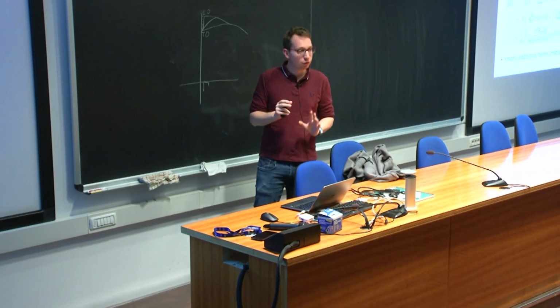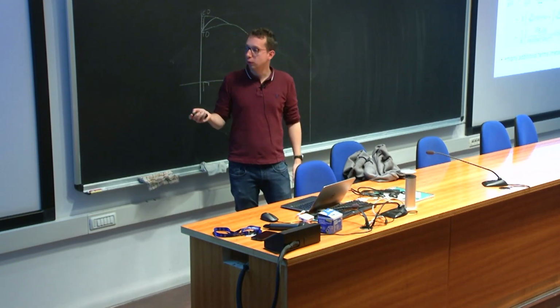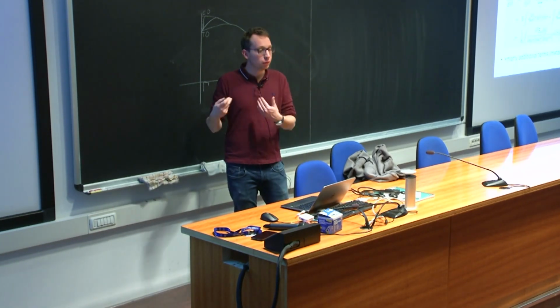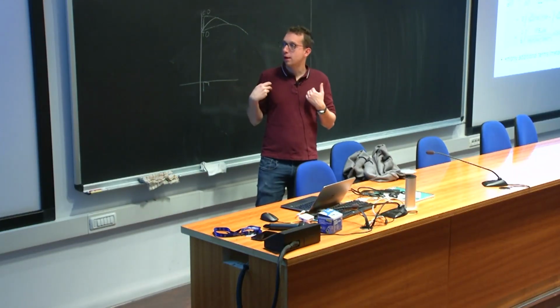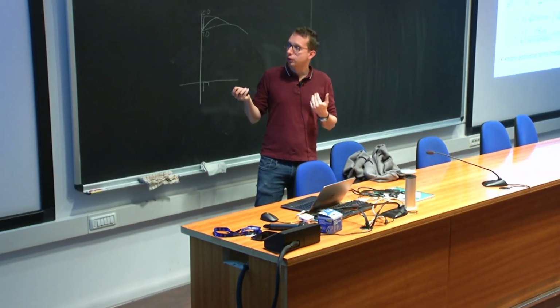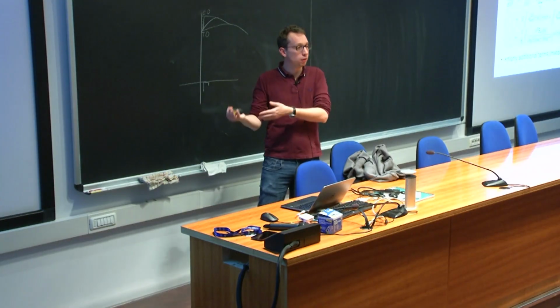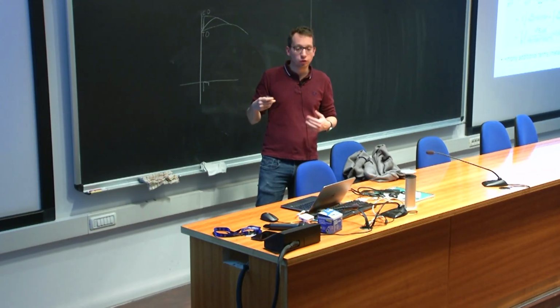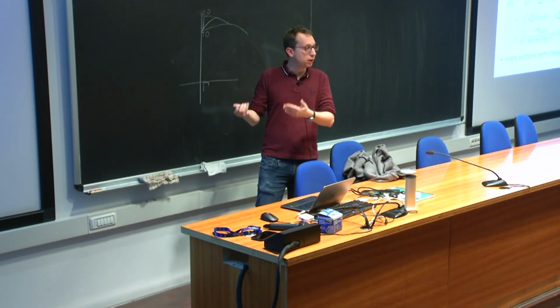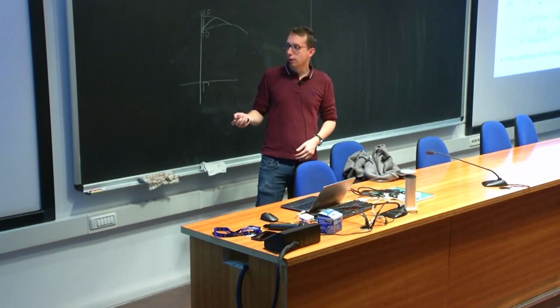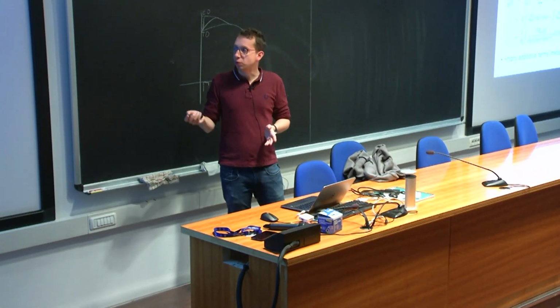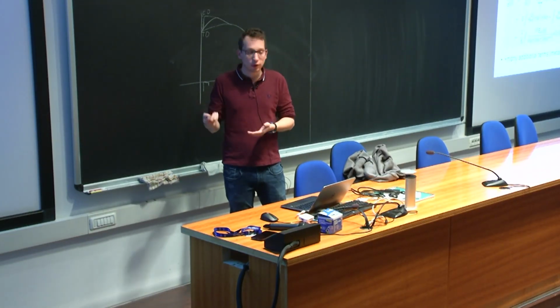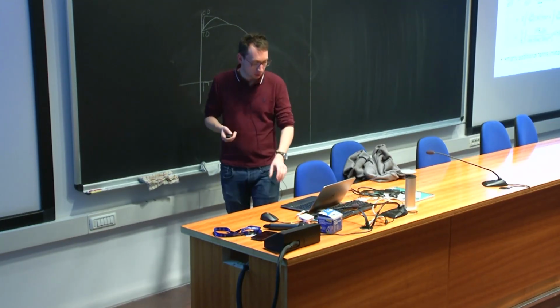So we say it's still a bit experimental, but it allows you to compute this quantity using perturbation theory and actually using the 2n+1 theorem, which comes again from Gonze, and allows you to compute the third derivative of the energy knowing only the first variation of the wave function. It's not the only way to compute the third derivative of the energy, but it is a quite effective way.